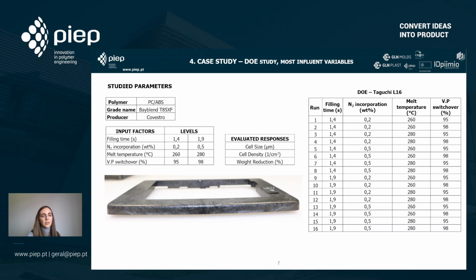In this case, the input factors were determined by an extensive literature review, and as we wanted to know specifically for this part which was the best results, we conducted this DoE with these four factors. So the factors were filling time, gas incorporation, melt temperature, and velocity point switchover. In this case, the velocity point switchover is the amount of material that is in the cavity.